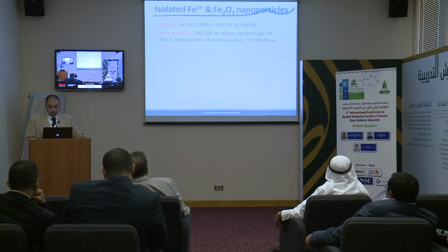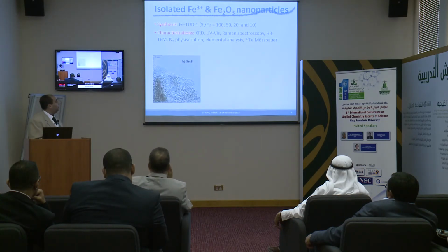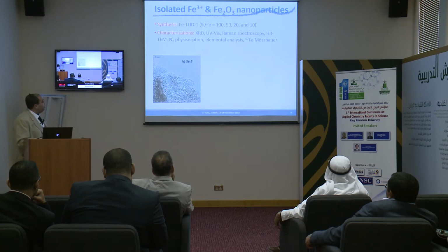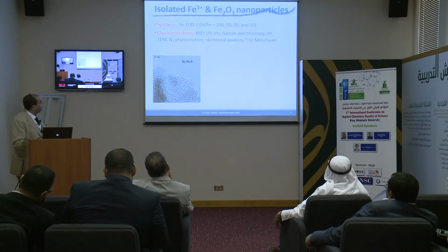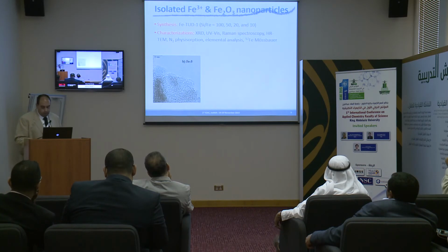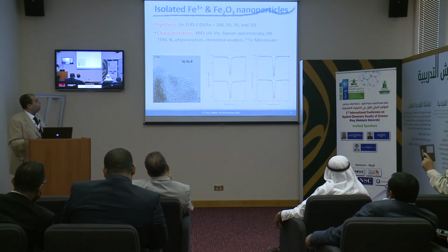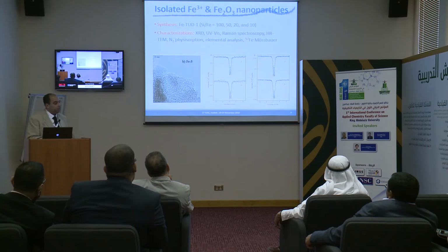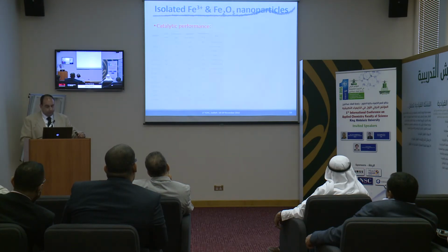We characterized it also by many techniques, and for the first time we could actually see the iron oxide nanoparticles embedded in the TUD1 by high resolution TEM. It's in a range of 5 to 6 nanometers. And by Mössbauer, we confirm the presence of this iron oxide plus the isolated iron 3 ion. Okay, let's go into the catalytic activity.